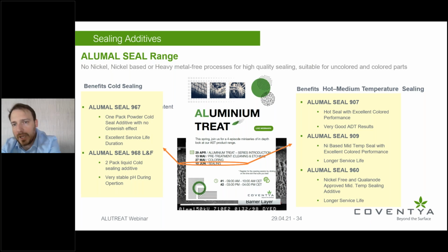Whereas on the hot sealing media, especially a new product that we have developed in our lab, the 907, is currently rolled out and has great success, and it does provide a unique solution to especially electrocolored and black samples which have the tendency to have a velvet-like feel or appearance on the surface, and they still provide a very good ADT result.